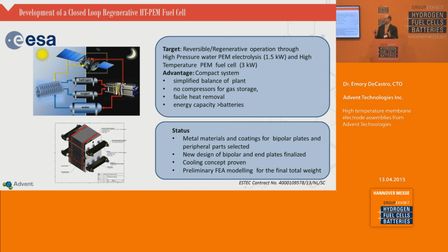Now you may ask, why high temperature? Why not low temperature? Low temperature is proven, it's good. The issue is this. In space, the only way to get rid of excess heat is through the radiative process. You're radiating heat to a vacuum. So there's no way to use a fan or things of that nature to cool. And so a high-temperature fuel cell operating at 180 gives you a smaller package, a lighter package, to get rid of the excess heat to space.